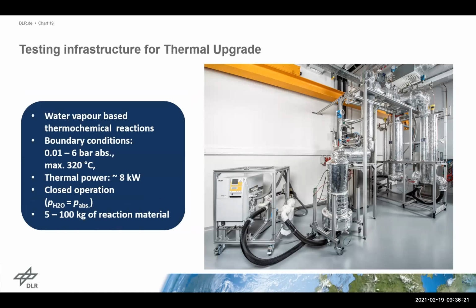We developed a test infrastructure for this thermal upgrade technology. You see in the back 2 large units, evaporator and condensers. They could be clearly smaller. The idea is that with this infrastructure, you see here some yellow measurement units, and they actually measure the filling level of liquid water inside of these tube bundles. And we have a gas connection here. And here is actually the solid reacting material, our thermochemical reactor. So we can measure the conversion by measuring the fluid level inside of this condenser and evaporator. The whole system can be operated up to 320 degrees Celsius with this thermostatic bath, and in absolute values between 10 millibar and 6 bar water vapor pressure.